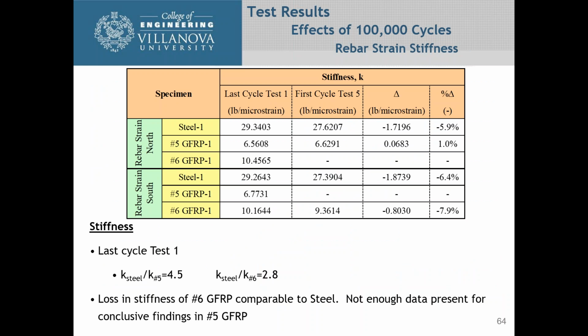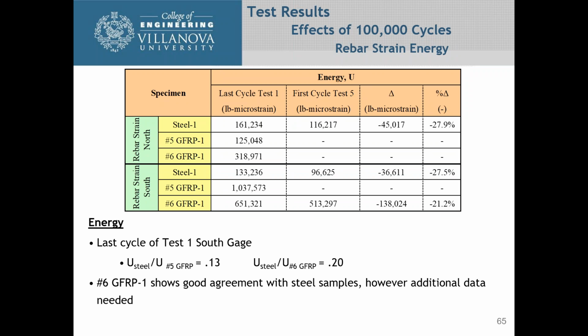So looking at the last test, the ratio of the steel to the number 5 was 4.5, and for the steel to the number 6 it was 2.8. So in looking at the graphs, you can see that the loss of stiffness for the steel versus the number 6 bar was primarily about the same. The number 5 bar we really couldn't make too many conclusions on, because we'd lost some information because of the failure of some of the strain gauges. So here again we're going to look at the energy, and you can see that number 6 is in good agreement with the steel samples, but again we kept losing the bond between the strain gauge and the GFRP bar, so we lost a lot of information here.